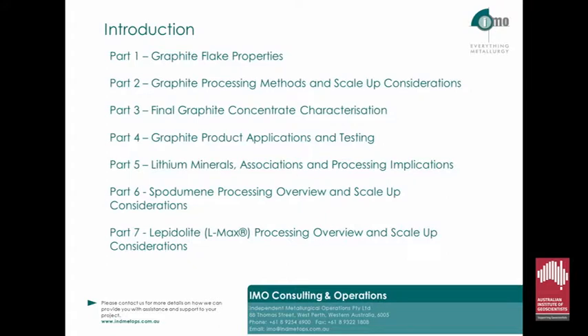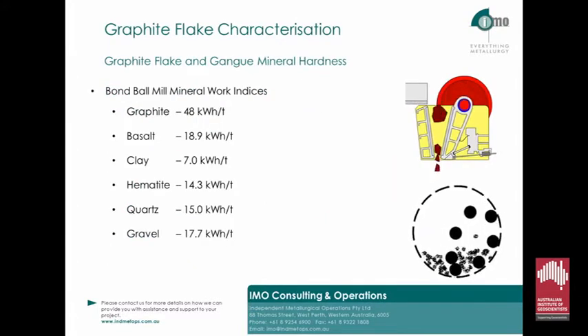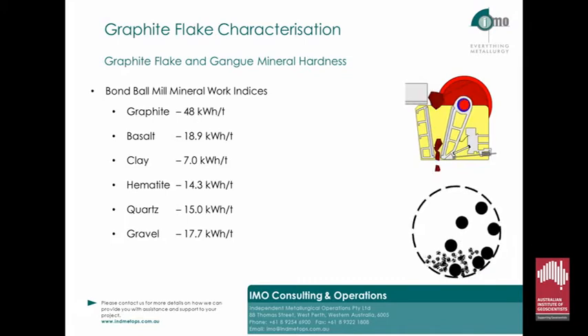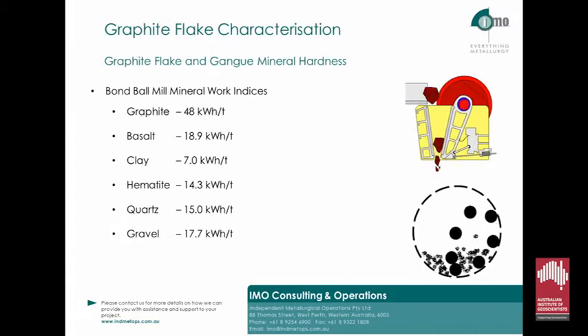The properties of the graphite flake itself are imperative to achieving a high-grade concentrate. I've learnt if the graphite has gangue entrained within the flake, it is going to be more difficult to achieve a high grade. I characterise a high grade as greater than 96% final carbon content. I think flake content has already been well characterised today.